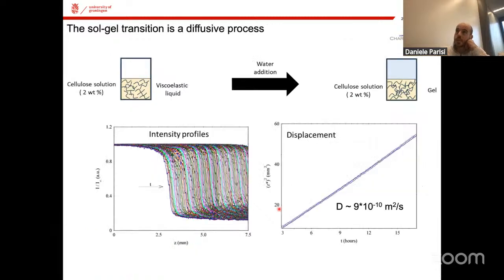So this means that if we just collect the autocorrelation functions as a function of Z, the depth of the capillary, and as a function of time, we get all these autocorrelation decay functions. So we can get the time at which each correlation decay exhibits, and plot it in this way. So we have Z squared, which is a sort of mean square displacement, as a function of time. And what we observe is that this square of the size as a function of time scales linearly. So it means that the gelation process is a diffusive process, something that was not very granted from the beginning.